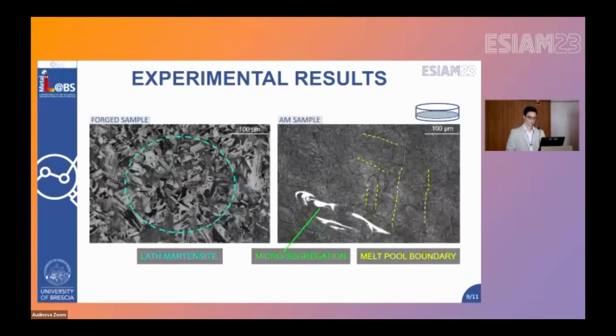So looking then at the microstructure of the analyzed sample, you can see that the first sample is almost completely lath martensite, and we didn't detect any relevant defect. On the other hand, looking at the additive sample, we see the laser scan track, because we tested the surface perpendicular to the building direction. So the first imperfection is related to the laser powder bed fusion process, and they are the melt pool boundaries that after just an aging treatment don't fade away.